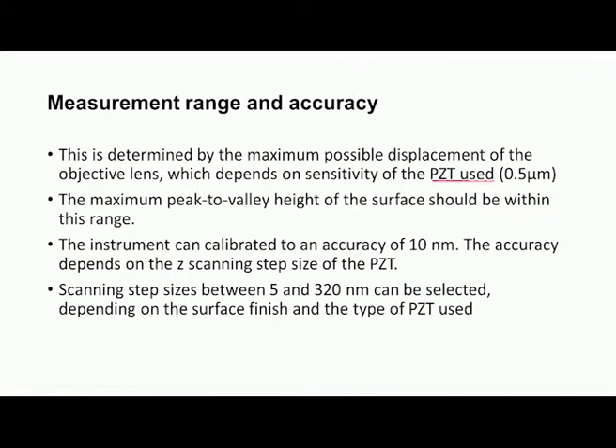Now, what is the measurement range and accuracy in such a system? The measurement range is determined by the maximum possible displacement of the objective lens. In other words, what is the maximum amount of movement of the PZT that is used. Typically 0.5 micrometer ranges are available, and the maximum peak to valley height of the surface should not exceed this range. That means if we roughly know the peak to valley height, accordingly we have to select an appropriate profilometer which will accommodate that range. And it is very essential that we calibrate the profilometers with standard specimens, and these systems can be calibrated to an accuracy of 10 nanometer.